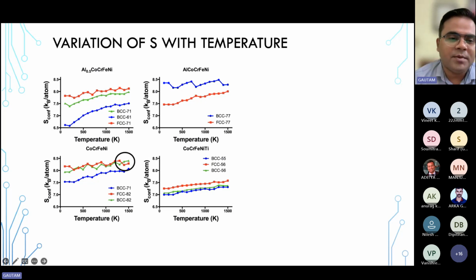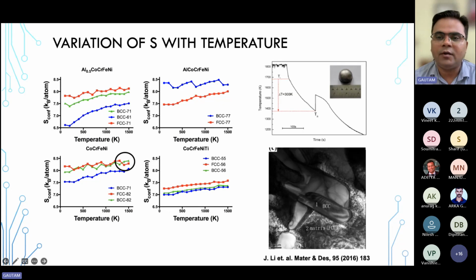So first of all, cobalt, chromium, iron, nickel was a difficult case, that is, why BCC is stable. And what we found later is that an independent group published a paper, and they showed that if you supercool a liquid of cobalt, chromium, and nickel, indeed BCC can get stable. So there is a BCC stabilization. So we made this prediction in our independent calculation, and later it was experimentally verified by the independent group. Similarly, recently in aluminium, cobalt, chromium, iron, nickel, a paper has come out where they've shown that BCC can also be stabilized, which we made predictions about earlier with the computational calculations.